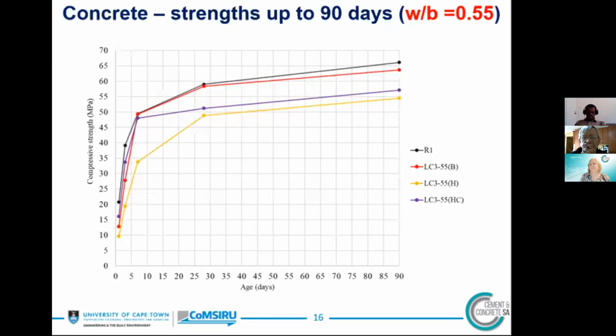Now again, here is the case of 0.55 water binder ratio. You can see at 7 days, the HC clay, which has low kaolinite content similar to H clay, but the strength of the 55 mix with HC clay is similar to the 55 mix with B clay and the reference mix. Now this again is because HC clay has higher internal surface area than H clay and absorbs much of the available water.